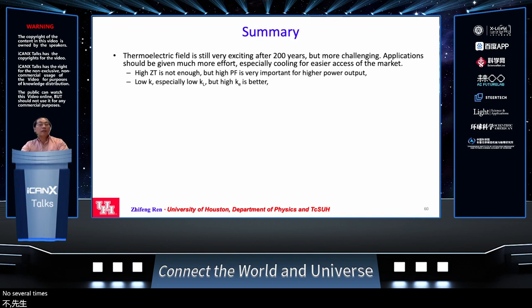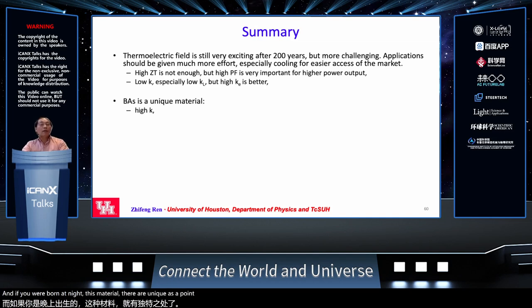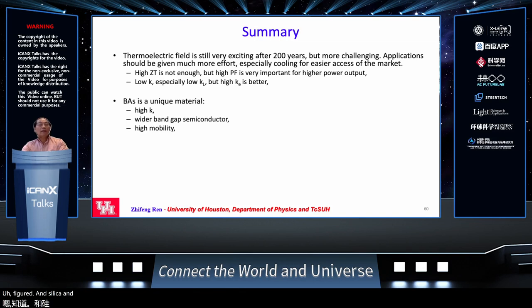Low overall thermal conductivity is not good enough, but we need to look for low lattice thermal conductivity but high electronic thermal conductivity so that your power factor is high. And for boron arsenide, this material is very unique. As I pointed out, not only does it have a high thermal conductivity, it's also a wider band gap semiconductor because the intrinsic band gap is 2.0, bigger than silicon. And it has not only high thermal conductivity, but also very high mobility.